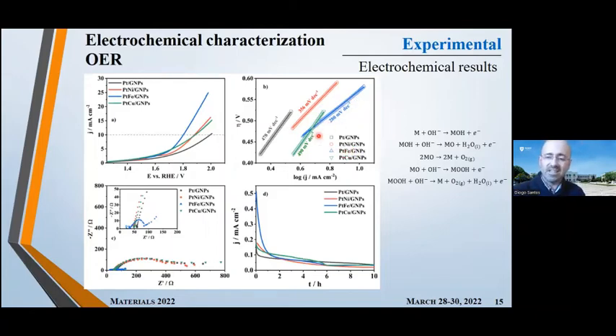So we want the Tafel slope to be low, because as you see, if this is overpotential and this is current, this means the highest increase of current for minimum change in overpotential, and that's what we want to see in practice in our URFC when we are in electrolysis mode.